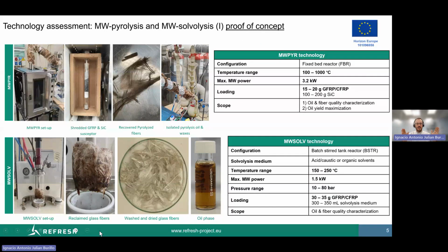So to carry out the proof of concept of this technology, we count on two different reactor units, the microwave pyrolysis process unit and the microwave solvolysis unit. Both microwave cavities can hold tanks up to 1 liter capacity, and what we were evaluating are the process conditions, so temperature, residence time, and also flow rates, to get the maximum in terms of oil yields and productivities, as well as clean fibers. So as you can see there, by pyrolysis, we are able to